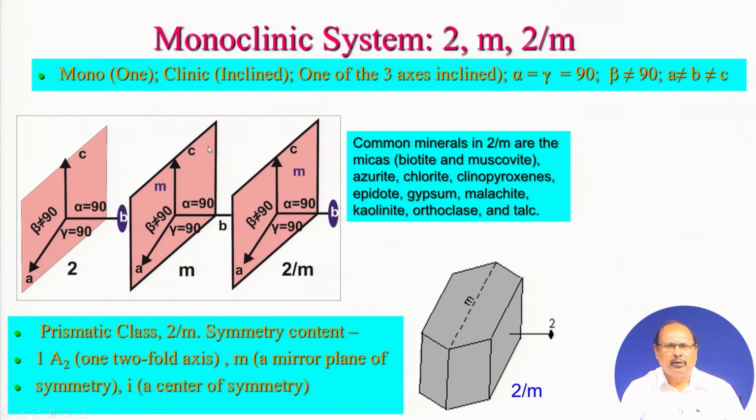In case of the monoclinic crystal system, if you have a two-fold axis of symmetry like this, you have the 3 crystallographic axes A, B and C. The B axis coincides with the two-fold axis of symmetry. That is why this two-fold diad symbol is here. So, this line is a two-fold axis of symmetry and this is your B crystallographic axis.